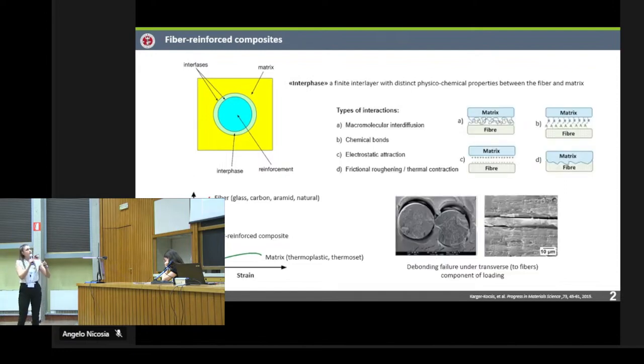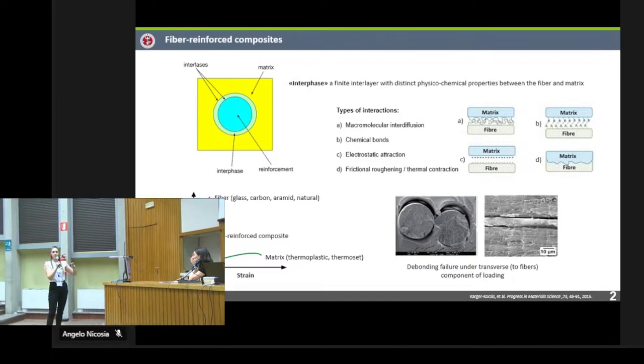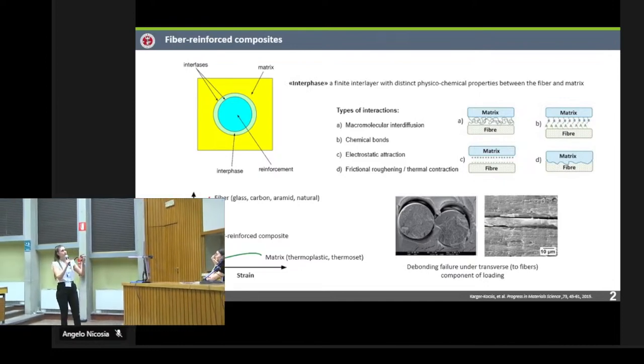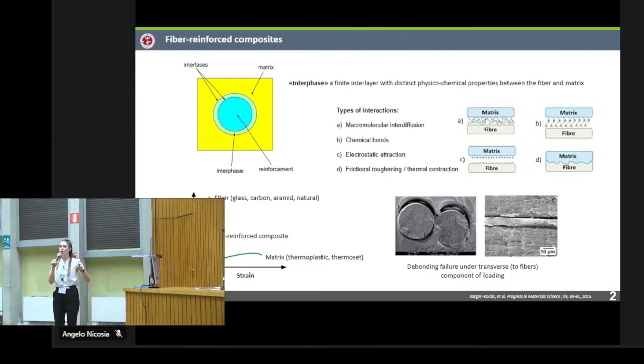Interfacial adhesion is dictated by different interactions such as macromolecular diffusion, chemical bonds, electrostatic attraction, or frictional contribution. But when the stress applied to the composite reaches a maximum value, these interactions can't withstand the load anymore, and we have debonding. Debonding is when the fibers and the matrix detach from each other and don't communicate anymore, so we don't have stress transfer from the weak matrix to the strong fibers. And this leads to the catastrophic failure of the composite.